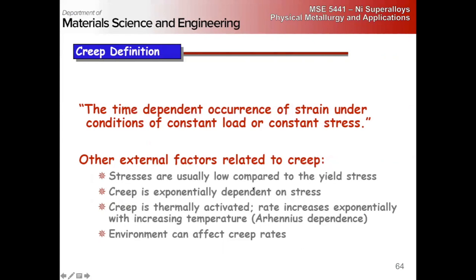And so the stresses for creep are usually going to be much lower than the yield stress, right? It's going to have an exponential dependence on the stress. So small increases in stress can have a very large change on the creep life. And because normally this happens at high temperatures, it's thermally activated. So it has an Arrhenius dependence with temperature, and the environment can also affect creep rates. Oxidation in particular can play an important role in the